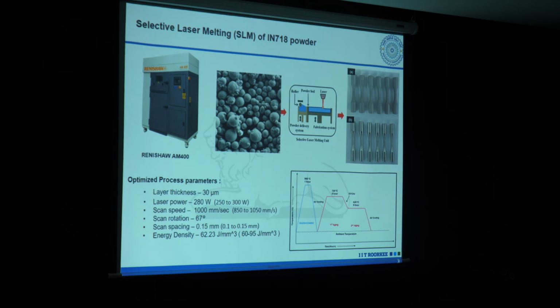We used a Renishaw AM400 machine for the fabrication of this alloy. Initially we had IN718 powder, procured from Renishaw, and we used the AM400 machine to fabricate fatigue as well as tensile samples. The as-fabricated samples have higher tensile residual stress, so we did some heat treatment to relieve the residual stress. The process parameters were already optimized, and the build layer was 30 micron. We printed one layer of 30 micron, then again 30. Similarly, we fabricated the samples in the horizontal direction.